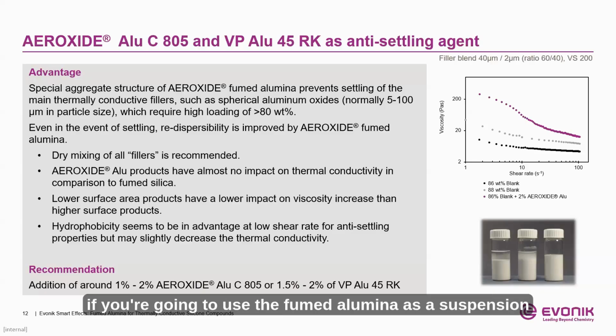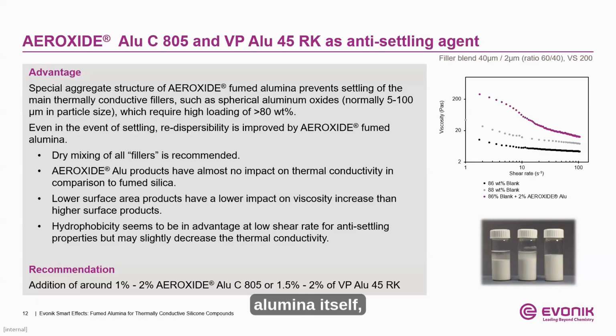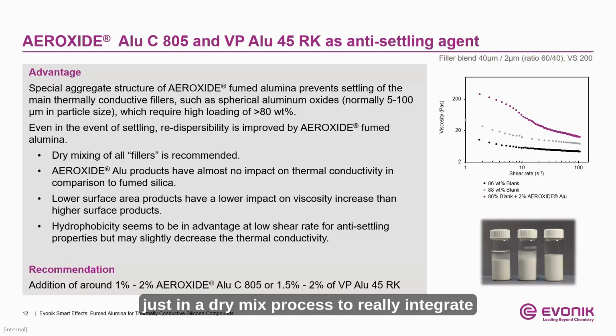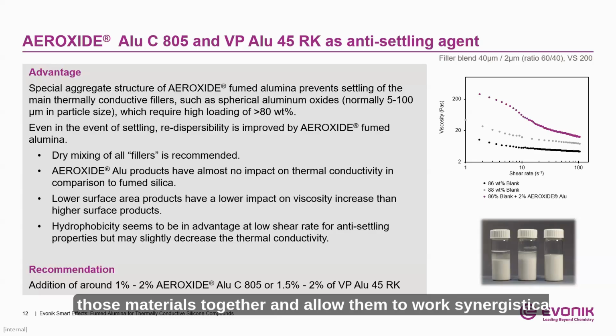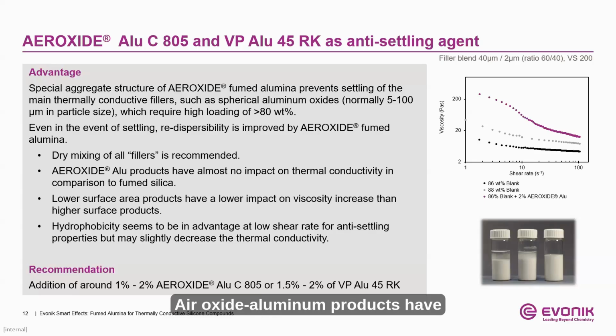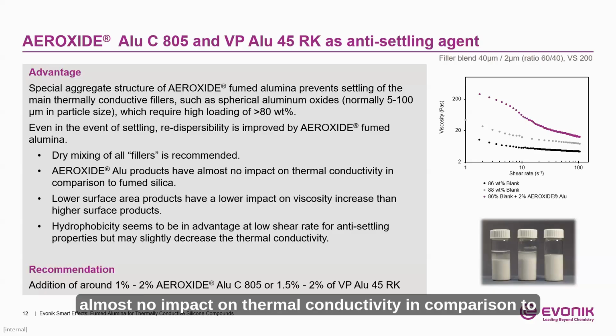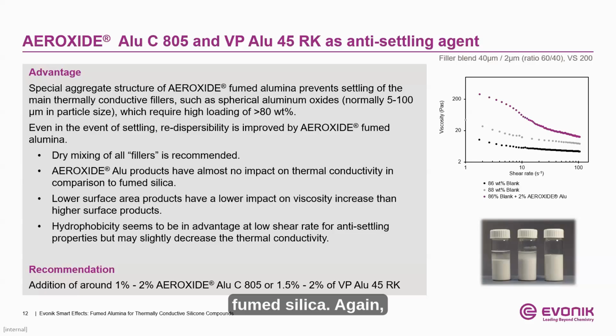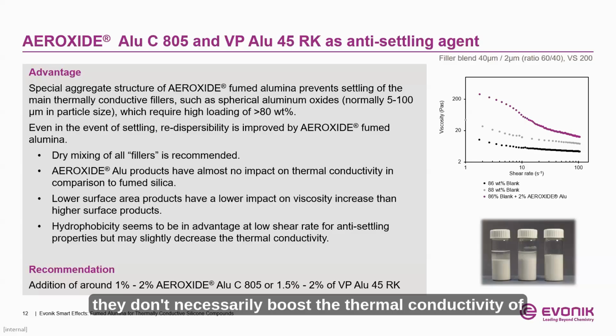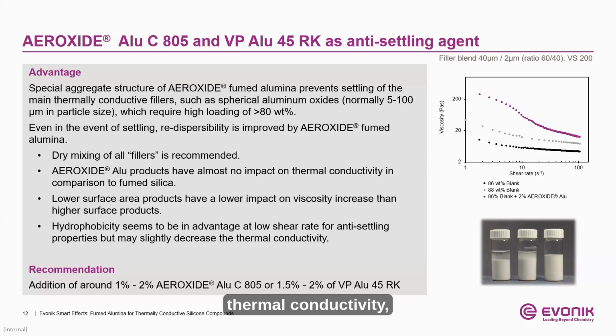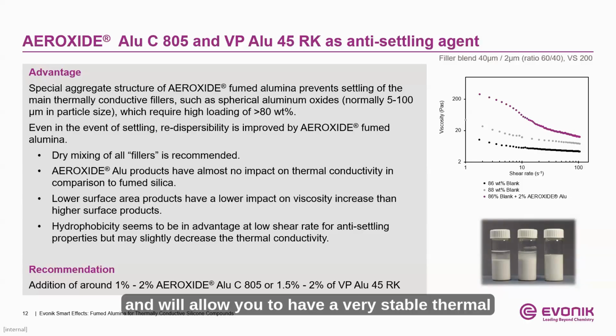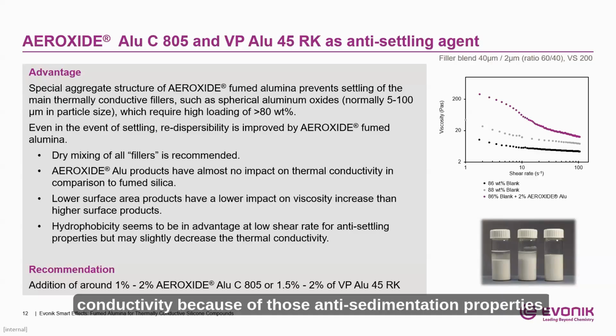Again, if you're going to use the fumed alumina as a suspension aid, you should always be mixing it with the spherical alumina itself, just in a dry mix process to really integrate those materials together and allow them to work synergistically in the final product. AEROXIDE alu products have almost no impact on thermal conductivity in comparison to fumed silica. Again, they don't necessarily boost the thermal conductivity of the material, but when viewed against fumed silica, which detracts from the thermal conductivity, your fumed alumina will actually allow you to maintain the same thermal conductivity, will not detract at all, and will allow you to have a very stable thermal conductivity because of those anti-sedimentation properties.